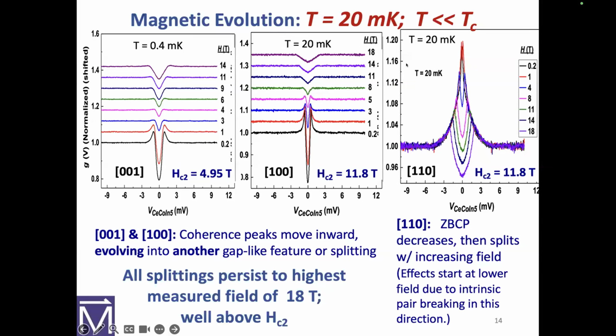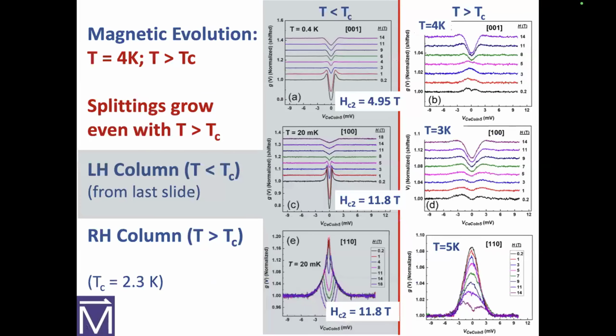Now, again, I said that I can't really explain the entire shape of the 110 data, but we can show you that we get some kind of splitting with zero applied field, and I mean with 0.2 Tesla. The argument for that is that you've already broken all the Cooper pairs at that 110 interface. So you don't have to break the Cooper pairs at that interface, because that interface is normal due to the sign change of the order parameter. Okay, so we've seen all this before.